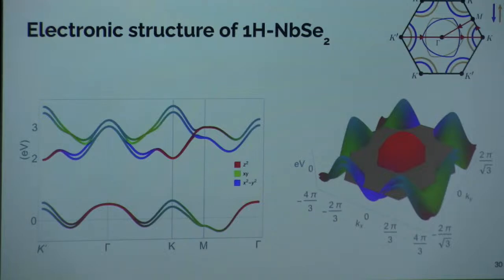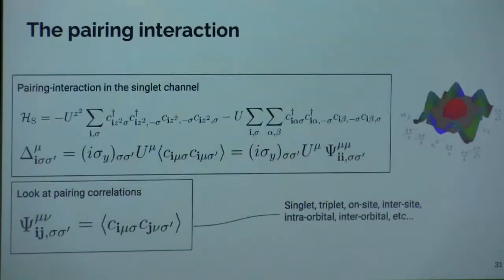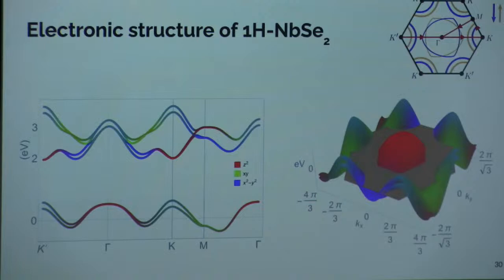So on the right, I show a 3D version of the band structure. The gray hexagon is at the Fermi level. So the intersection between the 3D bands and the hexagon allows us to visualize the Fermi surface. So you see that the Fermi surface is composed by a center red pocket completely dominated by the z² orbital. And at the K and K prime corners, the orbital content is completely dominated by the green and blue orbitals.